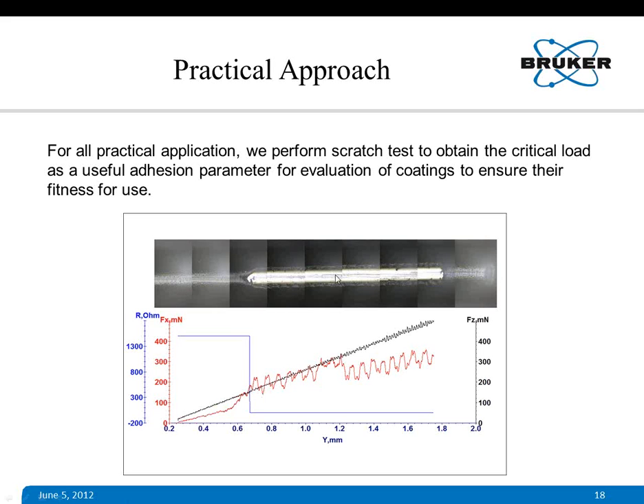and we drag over the coating surface and find out by several means, maybe by optical microscopy, where this coating is failing, or by measuring the electrical contact resistance. If the substrate is electrically conducting, if you continuously measure the electrical resistance between the tip, that is the stylus tip, and the substrate, we can easily detect the point of failure when actually the tip touches the substrate.